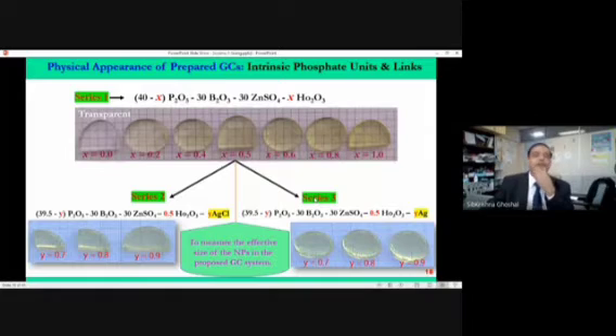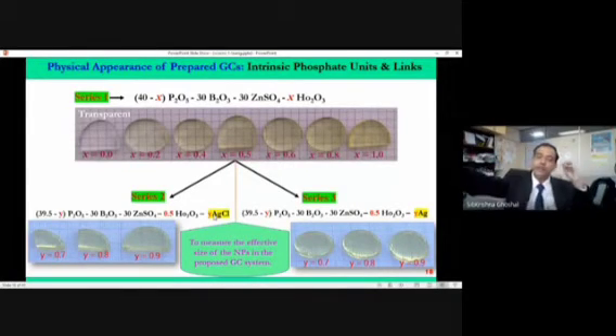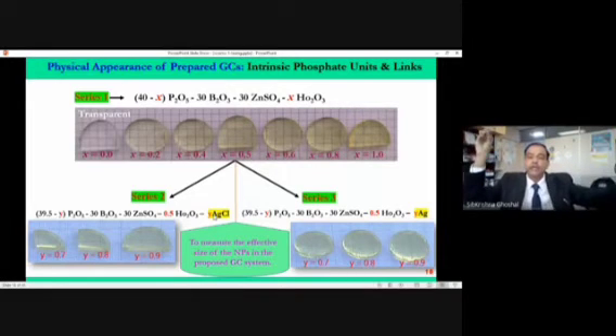So we basically prepare 3 series of glass ceramic material in this composition: borate, zinc sulfate, holmium oxide, and phosphorus oxide with the right weights, 40, 30, 30. This is called the nominal composition in mole percent, doesn't matter. So one series is with only holmium. In the second series, we choose the optimum concentration. Then we dope silver chloride. Silver chloride is cheaper than silver nanoparticle. So either we can buy silver chloride or we can buy silver nanoparticle.